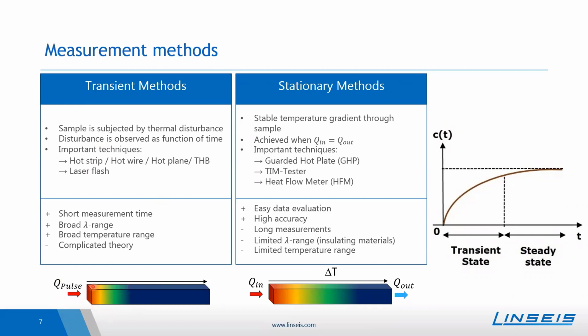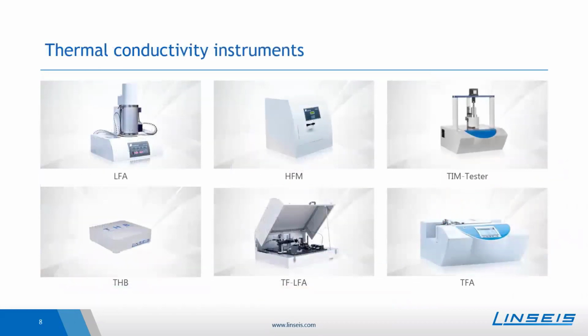Yes, so we will measure within that thermal disturbance in a material. Our product range for thermal conductivity instruments is rather broad. So we have the classical laser flash instrument and the THB for the transient methods, as well as the TF-LFA, the LFA for thin films, which also belongs to the transient methods. The second thin film analysis instrument, the thin film analyzer, shortly TFA, also measures according to a transient measurement method using a hot wire principle for the thermal conductivity determination.